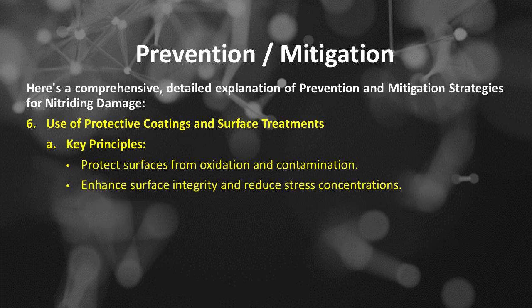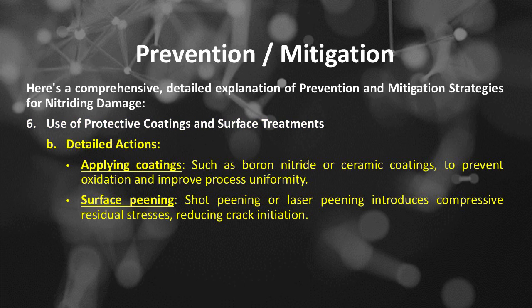Number 6 of prevention and mitigation strategies for nitriding damage is use of protective coatings and surface treatments. The key principles include protecting surfaces from oxidation and contamination, enhancing surface integrity, and reducing stress concentrations. Detailed actions include applying coatings, such as boron nitride or ceramic coatings, to prevent oxidation and improve process uniformity. Surface peening, shot peening or laser peening introduces compressive residual stresses, reducing crack initiation.